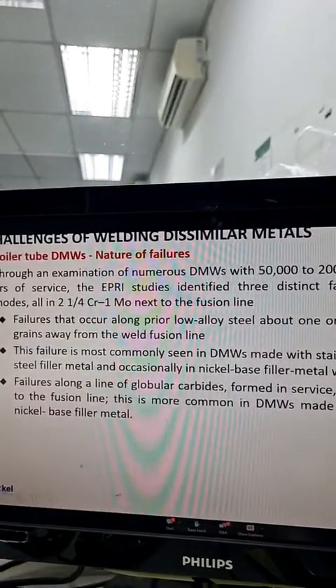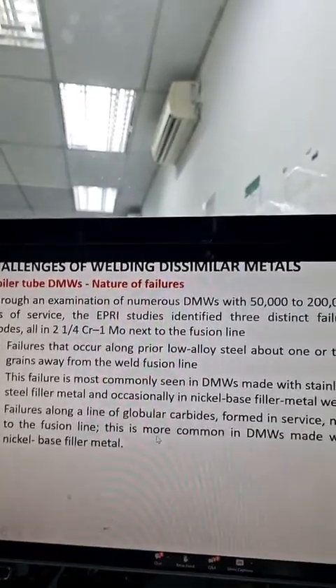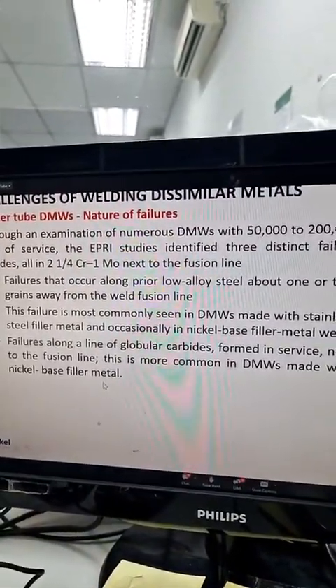Nickel-based filler metal. And another category was failure along a line of globular carbide formed in service, again next to the fusion line. So this was observed while the weld was carried out with the nickel-based filler wire.